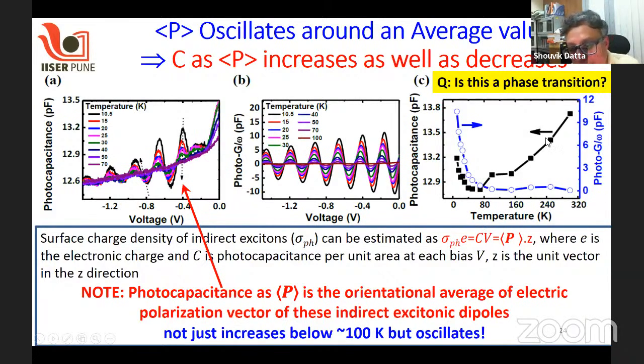Although the magnitude increases like a phase transition below these 80 to 100 Kelvin temperatures, you must also understand that it is not just the fact that the number of excitons is increasing at low temperature, because we know that capacitance is probing the effective polarization of these excitonic dipoles, and that not only increases but actually decreases, in a way oscillating around a certain value. So we know that these are some kind of phenomena which we see. Usually the capacitance of any semiconductor sample freezes as you go to lower and lower temperature. So this is definitely something very interesting.